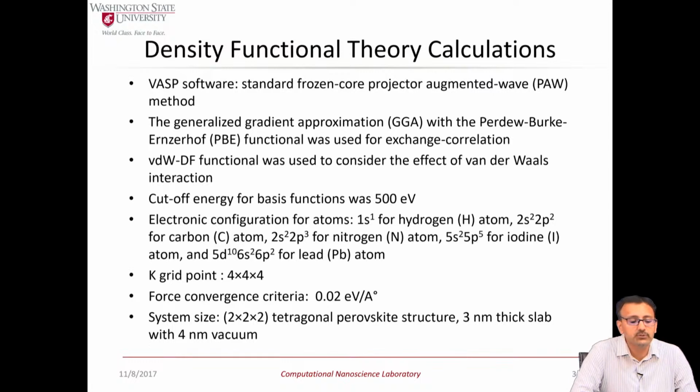Again, this is the detail. In this case, we used the software VASP, and we used a generalized gradient approximation with PBE functional for exchange correlation. We did account for van der Waals interaction, because this is an inorganic-organic lead halide. So that is kind of important. We used a functional for the van der Waals, and we did a sensitivity study for the parameters that we use, such as cutoff energy and force convergence criteria.